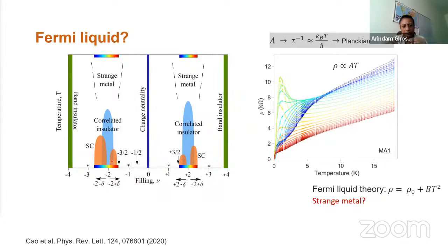As I told you, when the filling factor of the band is around half filling, which is because there are 4 maximum states, then half filling is essentially a filling factor of 2. When you have a filling factor of -2 or +2, there's a correlated insulating phase, and the superconductor is observed right next to that. And this is exactly what happens in many of these high TC superconductors, where a Mott insulating phase is in the center, and the 2 superconducting domes are next to it. So it's a doped Mott insulator. So that led to very many interesting questions.